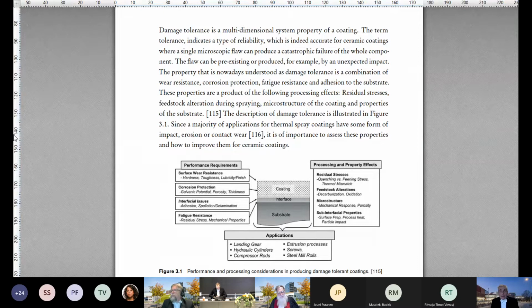Yes, why not? We've tested already with our HVOF coatings the gas permeability, and there are small gases that go through, larger ones that don't. Then if you would find the parameters to tweak in the spray process or the feedstock to somehow control the crack network, to have the crack size proper. If you want to filter out viruses, you want to be sure there's not one crack that is just a bit too big, or one crack path through the coating. But I can see this being of interest, like what we achieved with our HVOF coatings, a bit more throughput of larger gases.